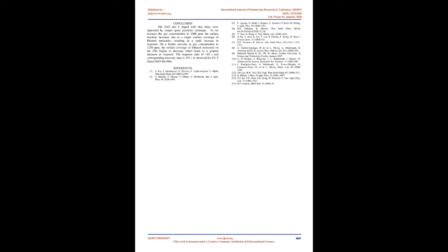Conclusion. The ZnO and F-doped ZnO thin films were deposited by the simple spray pyrolysis technique. As we increase the gas concentration to 1000 ppm, the surface reaction increases due to a larger surface coverage of ethanol molecules, resulting in a rapid increase in response. On a further increase in gas concentration to 1250 ppm, the surface coverage of ethanol molecules on the film begins to decrease, which leads to a gradual decrease in response. The response time of 145 s and the corresponding recovery time of 155 s is observed for the 4% F-doped ZnO thin film.